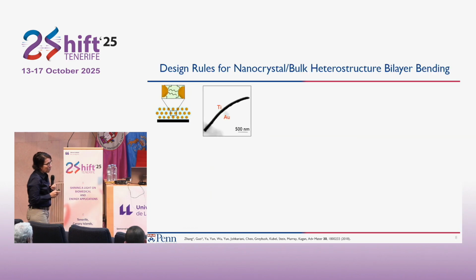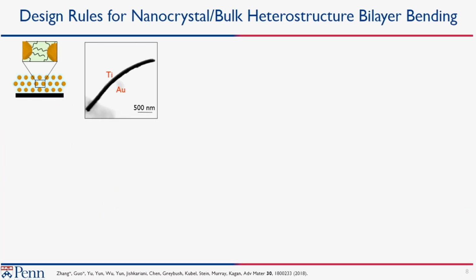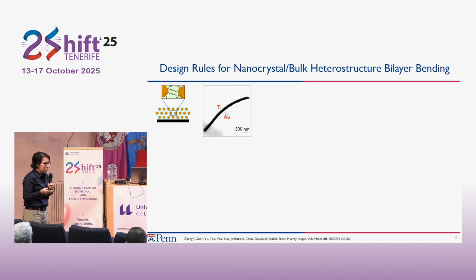We started with the example where we made the evaporated film titanium. We've since got a little bit smarter, for adhesion reasons, to change the metal underneath. But we put down a layer of nanocrystals. As I showed you at the beginning, the nanocrystals have ligands on the surface, and that provides some separation between them. If we made rods and released them up and studied them in electron microscopy, we have a thin titanium layer here, and this is the layer of gold nanocrystals. I won't say it's completely straight, but it's kind of straight.